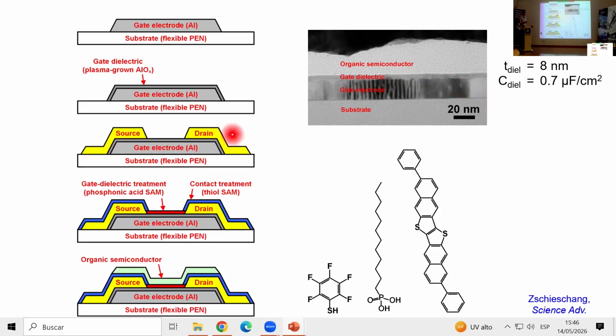Then we deposit the source drain contacts, pattern them by electron beam lithography to minimize the channel length and the overlap here. Then we functionalize the surface of the semiconductor and of the metal electrodes with these organic monolayers here. And then the last step, we deposit the organic semiconductor, our beautiful diphenyl DNTT.